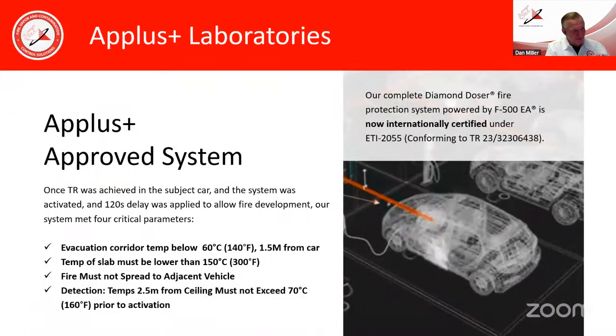So a few other things about this test. To achieve success in this test, there had to be 4 critical parameters met. The evacuation corridor, or that third space that was left open around the automobiles, that corridor temperature had to remain below 60 degrees Celsius, and it did, or 140 degrees Fahrenheit. So it had to remain a survivable space, and that had to be 1.5 meters from the car. Closer to that, it could be a little warmer, but 1.5 meters away from that car, the ability to escape and get away from it was maintained throughout.